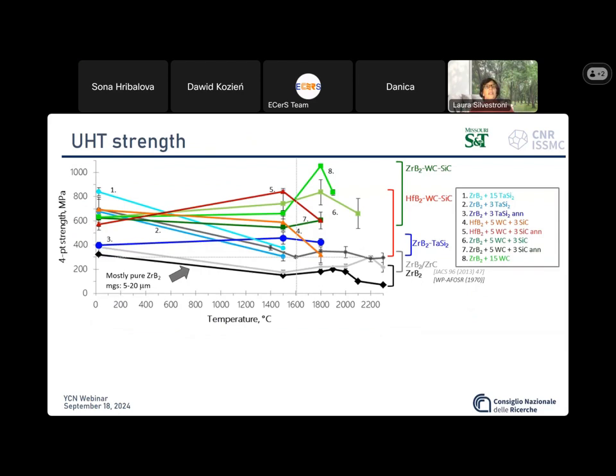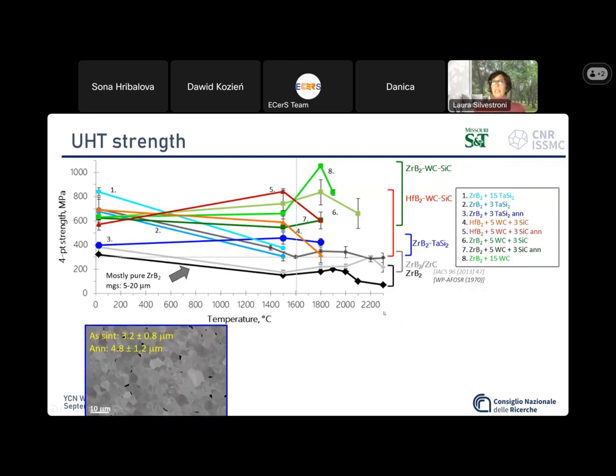Here I collect all data available up to the ultra-high temperature regime, which is commonly defined at 1600 degrees C. And here is a dotted line. You see the boundary of 300 megapascals, which is considered reasonable for structural application in the aerospace sector. So in gray and black, I reported data from mostly pure zirconium diboride obtained from the Air Force labs in the 70s and more recently from the MS&T group. Both of them were featured by quite a large grain size range from 5 to 20 microns, and as such the strength was not exceptional, did not exceed 400 megapascal and decreased to 150 megapascal.